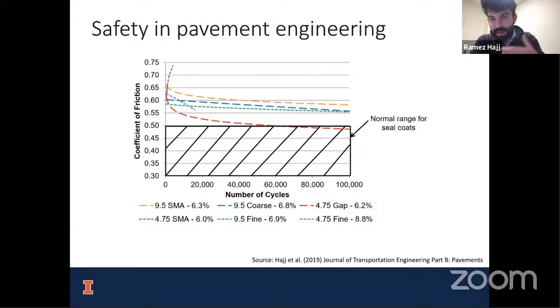And the reason is, as a pavement life progresses, you will see that the friction basically gets worse and worse because tires tend to polish the existing aggregates. So the surface friction interaction between tire and pavement gets worse and worse as time progresses. So what you will notice is a huge problem in terms of skid resistance or friction resistance in later ages. So typically what we do is we apply surface treatments. One such surface treatment is a seal coat. This is a single-sized aggregate adhered to the surface of the pavement with a binder. And this creates a nice friction surface, a good texture to restore that interaction between tire and pavement so that vehicles can stop in an appropriate manner.